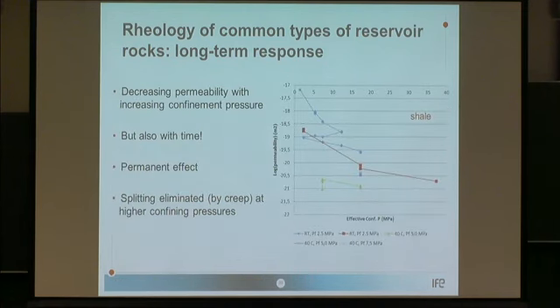And here are our in-house experiments on permeability of shales. Since we were involved in CO2 related projects, our interest was to measure the permeability of shale, to know what to plug into our models. What we did was put the sample into the box and squeeze it from all sides isotropically, and we looked at how permeability changes. Then we unload and we see that there is a permanent effect. We load again, and permeability reduces again. But then at this point the experiment was interrupted. Nothing happened, but the specimen was still there.